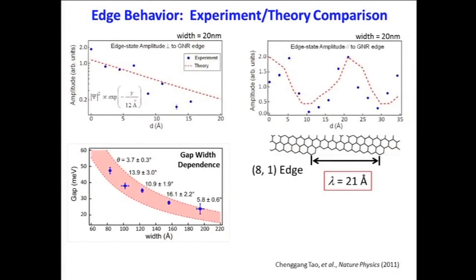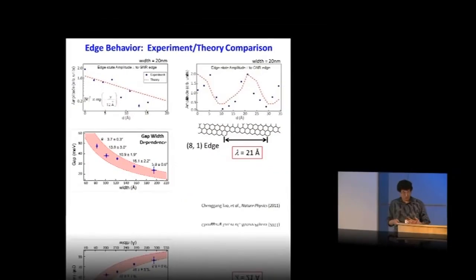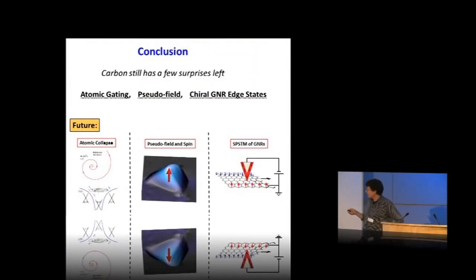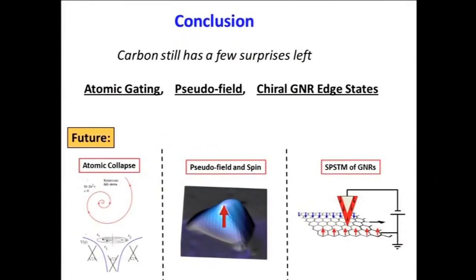And so you can see there's pretty good agreement between experiment and theory here. So I feel that this is very strong evidence that we are seeing an edge state for these graphene nanoribbons. And this edge state has an energy gap that is width dependent. So that's where I want to stop. And I'll stop just by concluding that I think carbon still has a few surprises left.